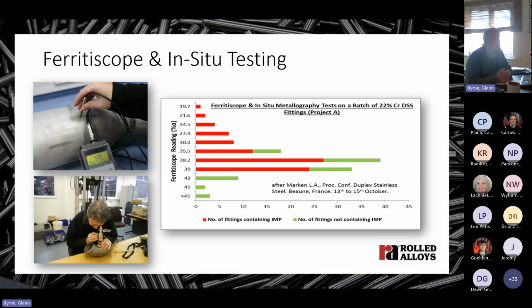Now, you can map out on parts any areas of low readings like this chap's done here. And then what he's doing is he then polishes and etches an area locally within the low reading range, and then uses in situ metallography to look down this microscope at the part. If he sees any of those black particles under that microscope, he knows he's got a problem. He's confirmed the diagnosis of sigma phase.